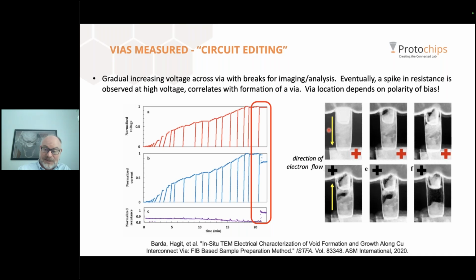The authors also found that the location of this void depends on the polarity of the voltage. Positive bias on the bottom electrode causes a void at the top, while a positive bias on top causes a void in the middle. So the benefit to the customer here is that by identifying the physical cause, they can now target a more effective solution.